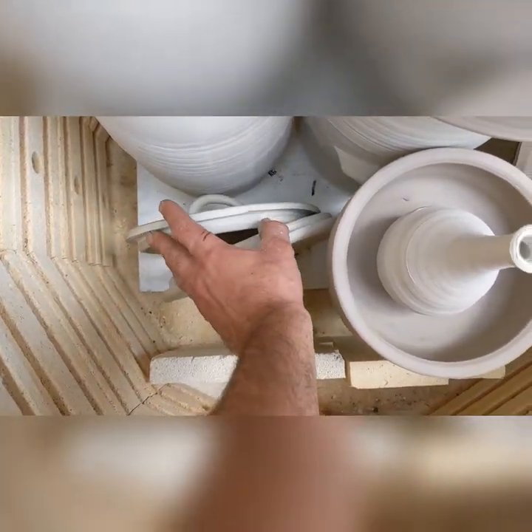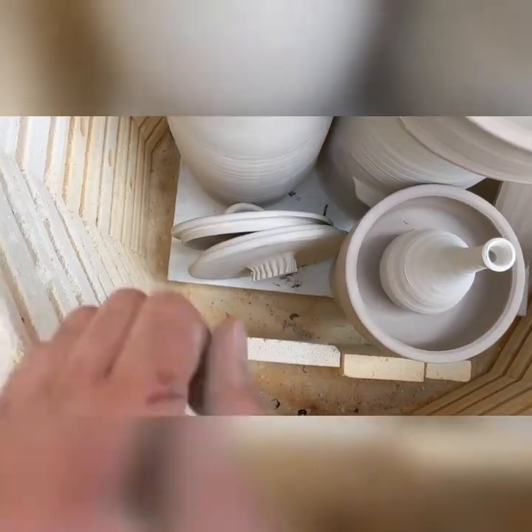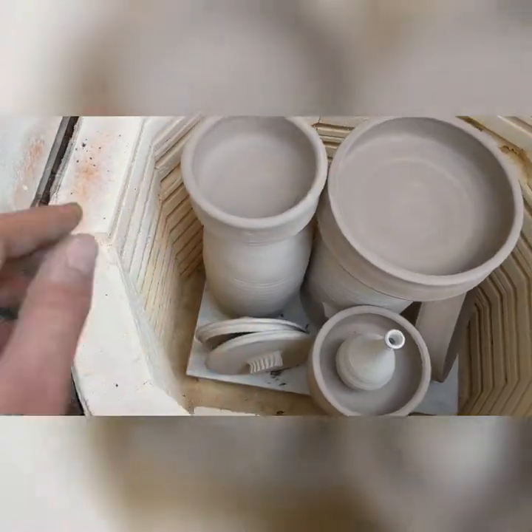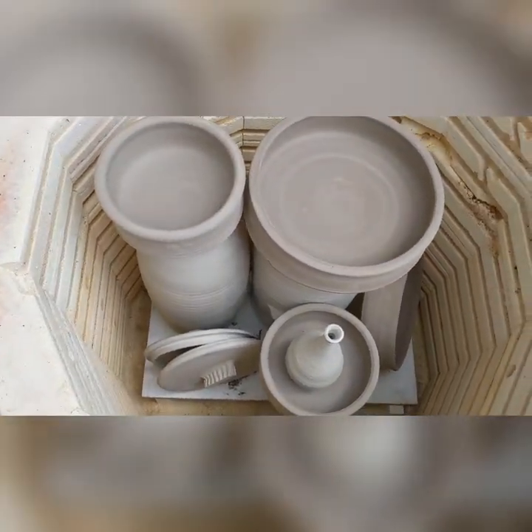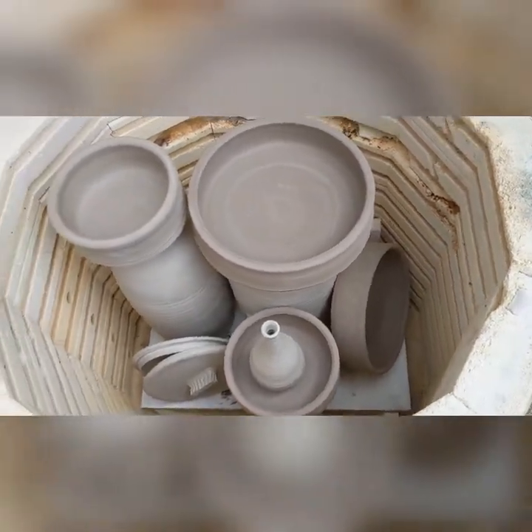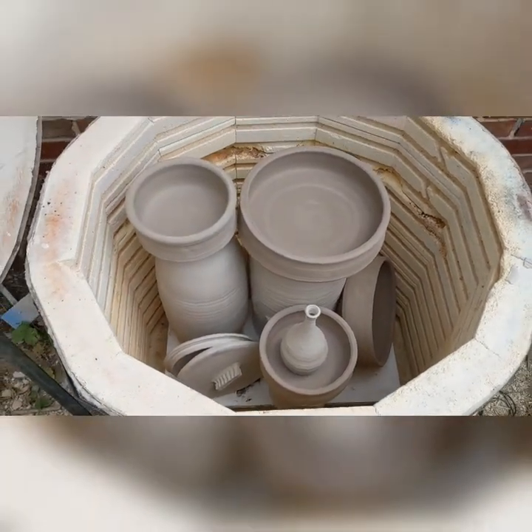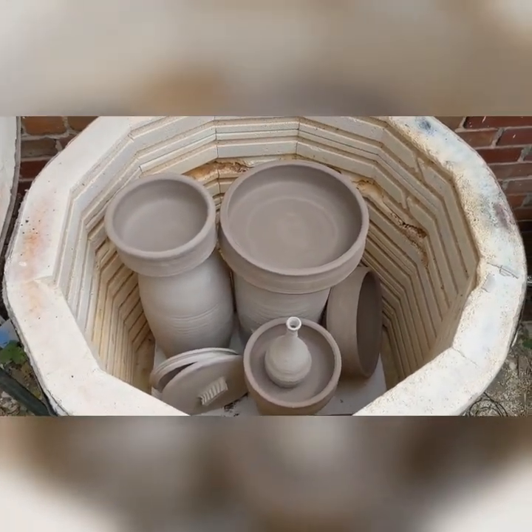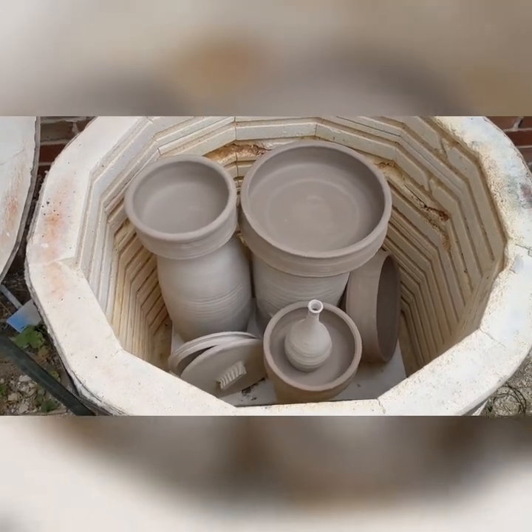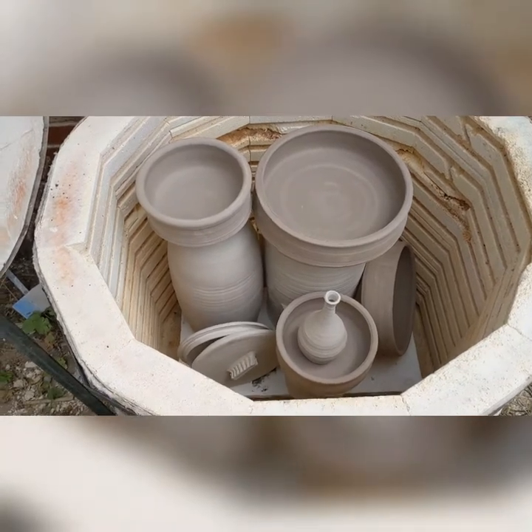I will, however, probably move them in a little bit so that they're not in the flame path over there. Differential heating can cause issues in quartz inversion, and so I don't want it to get blasted on one side of the lid and not on the other. In bisque firing you can stack things — this is called tumble stacking, where I've just fully filled the kiln without using any shelves. If I'm doing smaller items, I'll oftentimes use some shelves but still stack things in between.